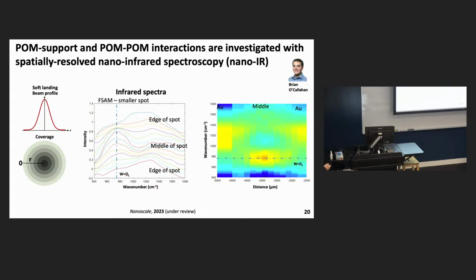And the data is shown in a different form on the right-hand side. And you'll notice that it's most intense around 1020 at the edges and most intense around 900 at the center. So what's the interpretation for that? Well, at the edges, you basically have clusters that are in contact with the surface that are far away from each other. They don't really interact or see each other. As you move closer to the center, these clusters become much closer at higher coverage. They begin to interact. And at the very center, it's possible they may even be piled up on top of each other. So instead of having an interaction with just the monolayer, you may have clusters interacting with clusters that previously arrived on the surface.